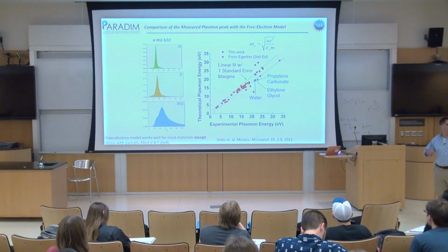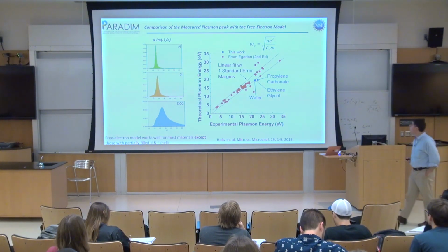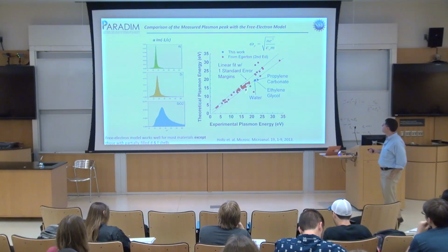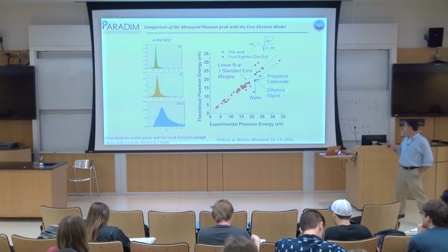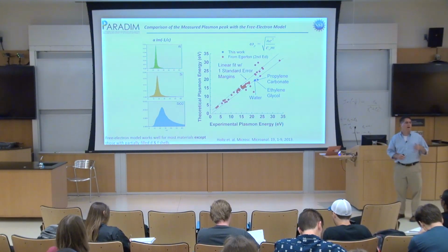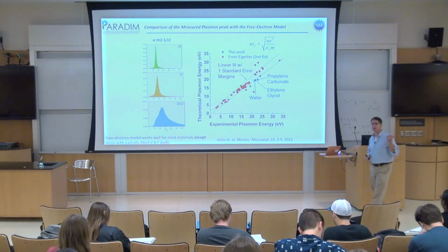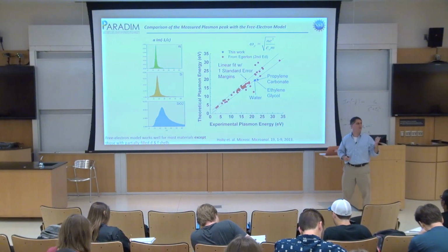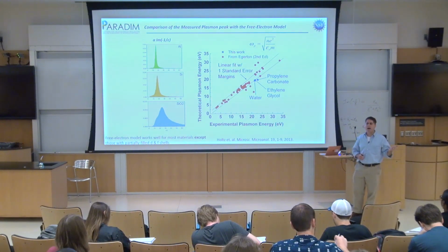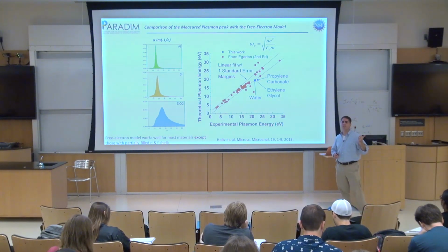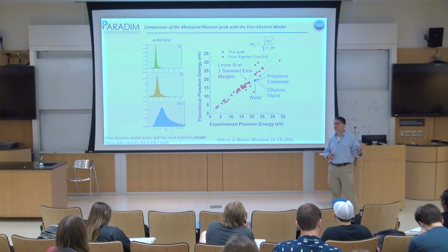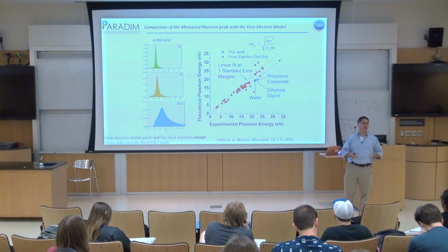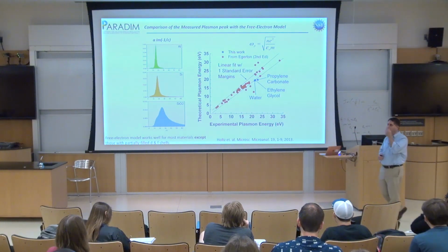So what we often do with this is, most materials, funnily enough, have plasma frequencies of about 20 to 25 eV. That's a typical electron density of most things. And there are a couple of elements that fall outside that range. But you can use this change in density. Paolo mentioned that someone was trying to measure temperature changes by measuring the shift in the plasma frequency. And that works. The other thing that causes a shift in the plasma frequency is strain. And don't ask me how that can tell temperature changes from strain when you heat up the material and the expansion coefficients of the material change as well. But good luck to them.